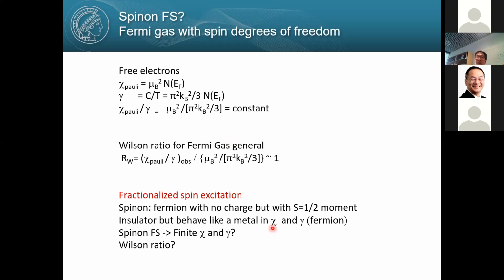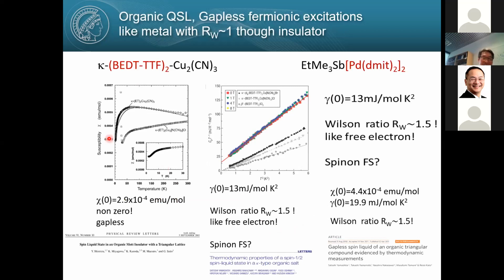Now, suppose we have a fractional spin excitation that is gapless. They have spin 1/2 moment and form a Fermi surface. They could give rise to Pauli-like susceptibility and specific heat gamma T-linear. And of course, the same phenomenology can be applied. So therefore, naively, we might expect a Wilson ratio for the T equals 0 limit susceptibility and the T-linear term. And here actually you get something like 3 times 10 to the -4 for the T equals 0 limit susceptibility.